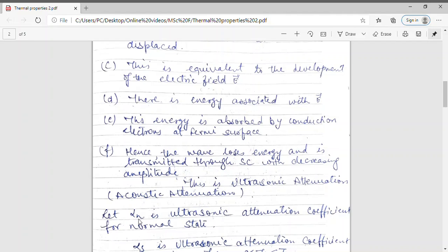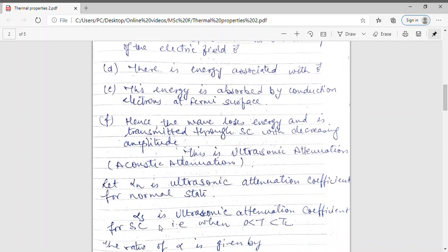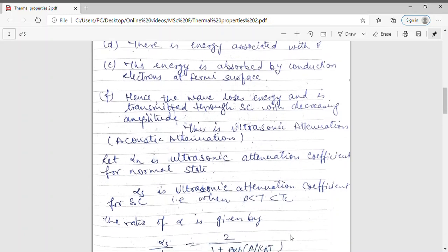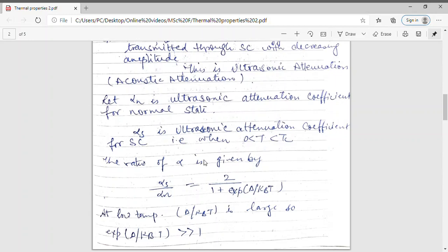For this purpose, let alpha n be the ultrasonic attenuation coefficient for the normal state. And similarly, for the superconducting state, I am taking alpha s as the attenuation coefficient. Here it is important that temperature is between 0 and Tc, because above it the material will become normal. The ratio of these two attenuation coefficients, alpha s to alpha n, is given by the relation equal to 2 upon 1 plus exponential delta upon kBT.